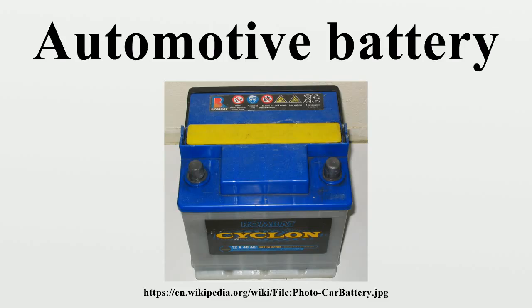One battery manufacturer even prefers storing new batteries on concrete in the summer to keep them cooler, decreasing the natural discharge rate. Early batteries had wooden cases, and could absorb moisture from wet concrete, giving current a route to discharge. Another explanation for the admonition to avoid concrete is that wooden cases in the earliest batteries encased a glass jar, which could be broken by swelling wood if the wood casing became damp. Later hard rubber cases were porous and had a high carbon content, leaving another route for current leakage. But modern polypropylene cases are at least 5 times more effective insulators than rubber, and the terminal seals typically do not leak as they once did.